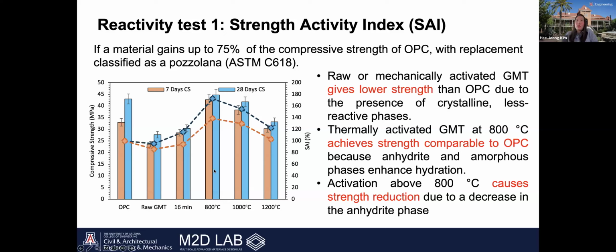But when GMT is optimally treated at 800 Celsius degree, the strength increases significantly and becomes comparable to the OPC sample. And this improvement happens mainly because of two factors. First of all, the formation of anhydrite, which supports the hydration process, and the increase in amorphous content, which makes the material more reactive.